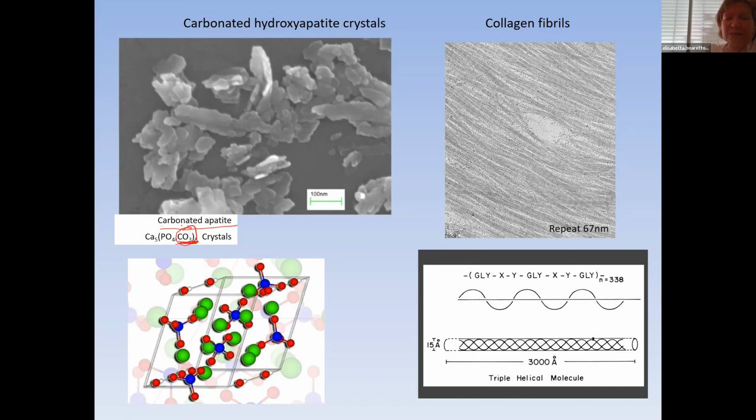But since it is a carbonate group, it can interact with the environment, and water can bring new carbonate and exchange with the carbonate in the bone, and then your pristine C14 signal in the bone is contaminated. So it's not possible to distinguish which is the original carbon and which is not the original carbon.